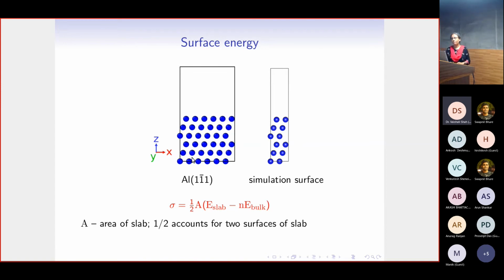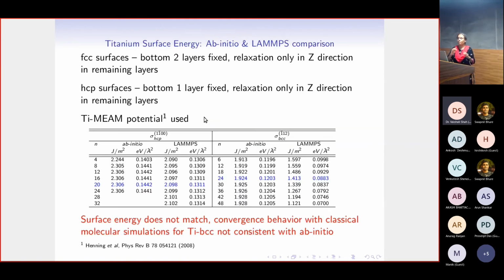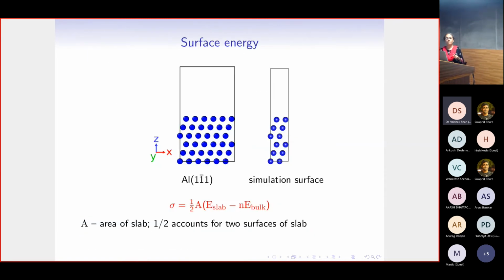And when we do the surface calculation, we have to ensure that there is a vacuum in our simulation between the topmost layer of the surface, because these are periodic repetitions along the x, y, and z direction, there is no interaction between the top layer in the simulation cell and its periodically repeated images. So there has to be enough vacuum between the topmost layer of the surface and where your simulation cell ends.